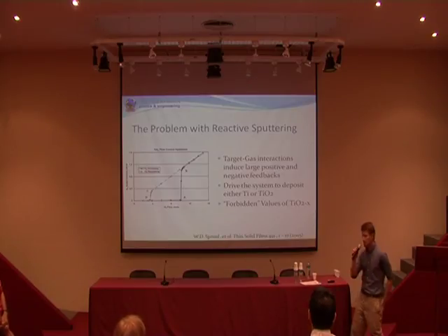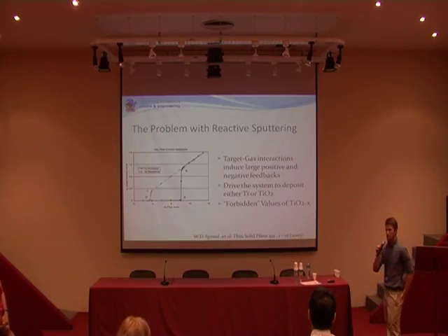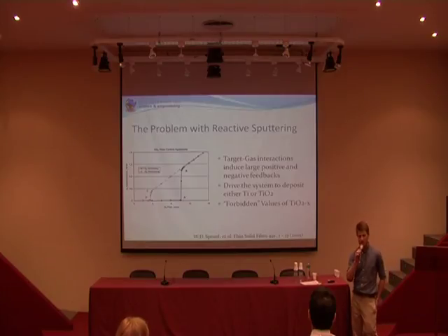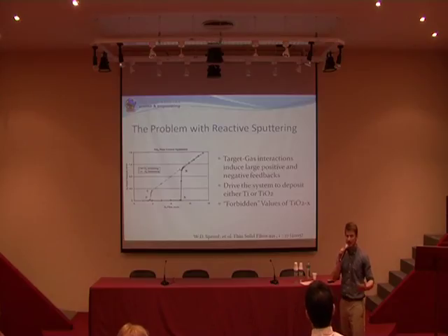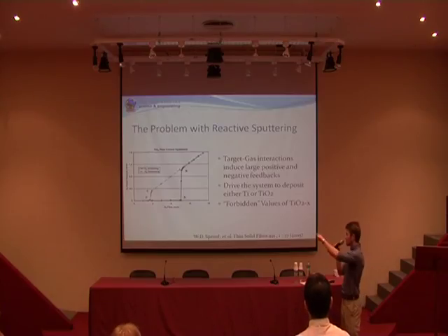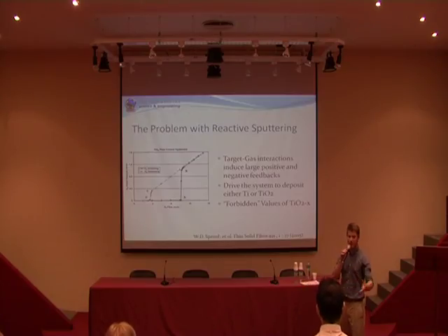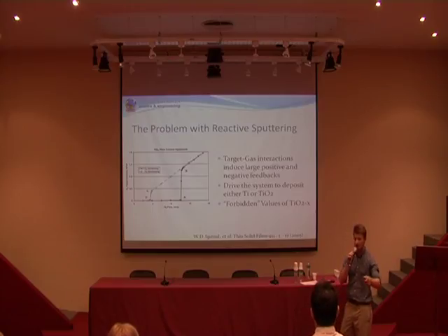And so in general, you still want to use the Berg model to stabilize it, because you will still have oscillations. That's what you can see in the literature. But if you combine all these elements together, you'll have the maximum effect. So if you don't have an S-shaped curve and you have this kind of active feedback, you'd probably be in the best shape for reproducibility.